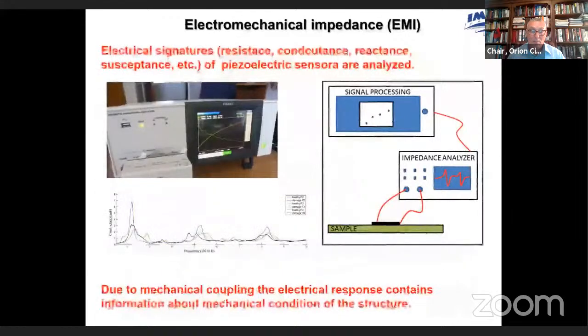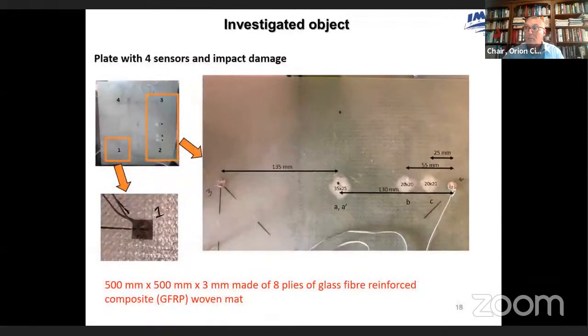The second method that I would like to present is the electromechanical impedance, where we investigate the electrical parameters as a function of frequency. These electrical parameters are measured at piezoelectric sensors that are bonded to the inspected structure. Here is a GFRP plate instrumented with 4 sensors, and the damage that was introduced here was impact damage. There were in total 4 impacts, 2 made at the same location, A and A prime. Next there was a B impact and a C impact in such sequence. All of these impacts were made with 30 joule energy.